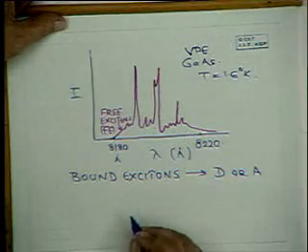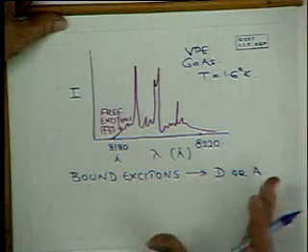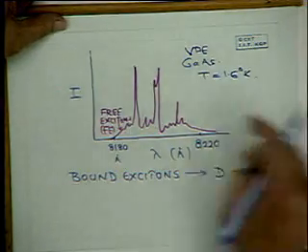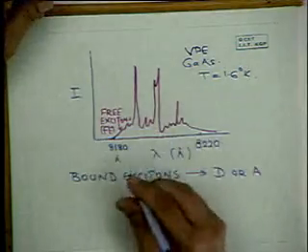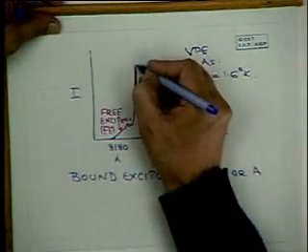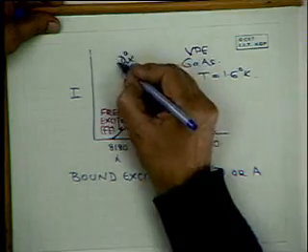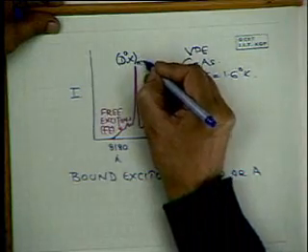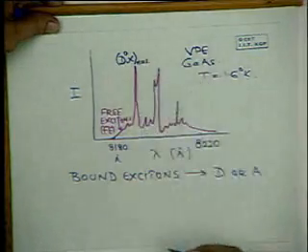And these donors and acceptors can either be neutral or charged. Typically, in the case of gallium arsenide, we find that this peak intensity is due to excitons bound to neutral donors and having a ground state n is equal to 1.